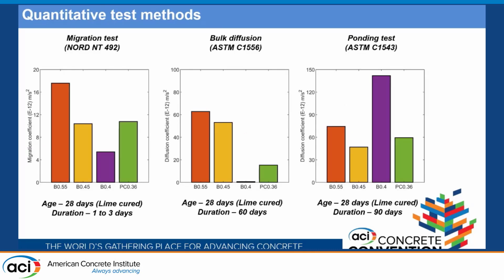Now let's move on to the results of the quantitative test methods. The first one is the migration test, which gives you the value of migration coefficient. A low value of migration coefficient is good in terms of having low chloride penetrability. So you can see that BCSA specimens seem to have a reduced migration coefficient as the water cement ratio reduces. So that's good. But when we look into the results of the bulk diffusion and ponding test, we see a sharp contradiction. Here you can see that the values are significantly higher,